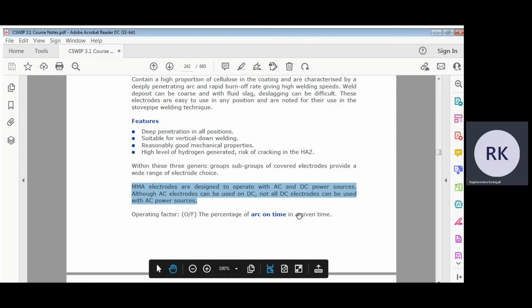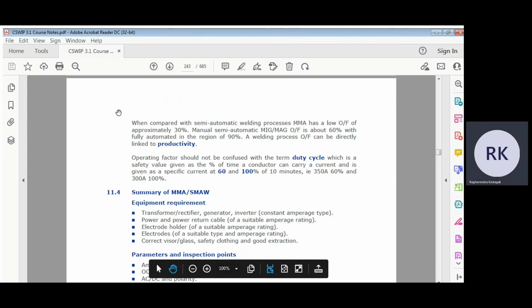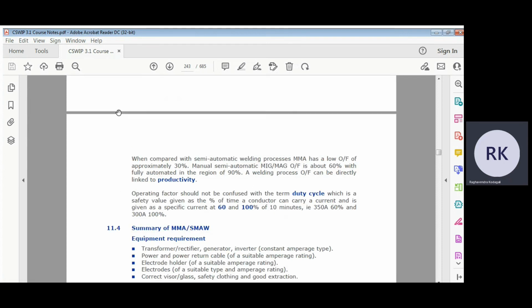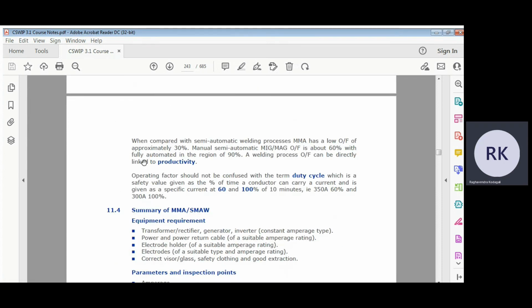So operating factor is the percentage of arc time in a given time. When compared with semi-automatic welding machines, MMAW has a very low operating factor. As we have seen in the earlier chapter, the efficiency is poor. So efficiency is approximately 30%. Because a lot of this activity is manual, it does not have good productivity. All the line managers I have seen, they don't like this process because of the productivity issues. Manual or semi-automatic MIG-MAG is about 60%. With fully automatic it is in the region of 90 to 95%. The highest is for the SAW machine, which has an efficiency of almost 1. So you need to know that it's a very highly productive machine.